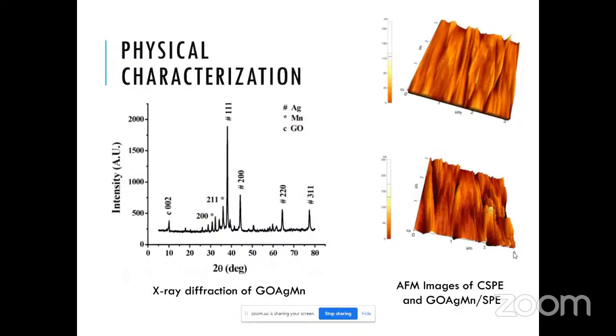For characterization, XRD reveals the presence of carbon, silver, and manganese species in the synthesized sample. And we can see a bare screen printed electrode and a screen printed electrode coated with the prepared catalyst in the AFM images. The increased roughness for the sensor electrode with the catalyst coated material is one among the reasons for the increased electroactive nature of the sensor.